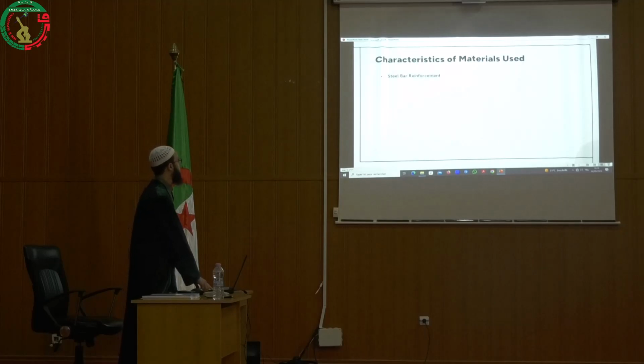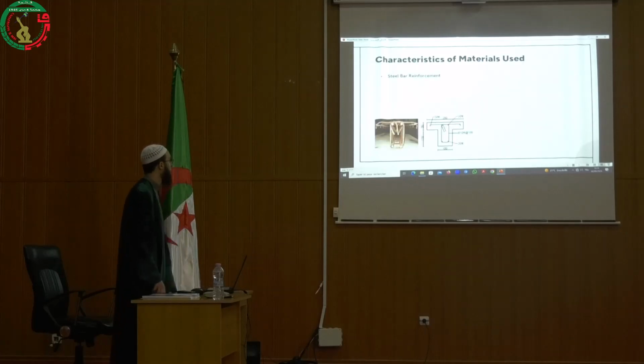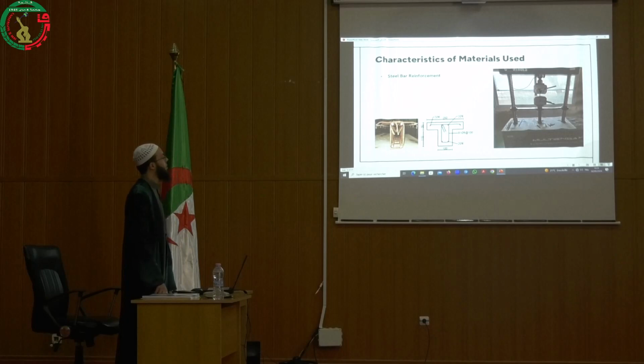Moving on to the steel bar reinforcements. We used identical 8 mm diameter bars for the tension zone, and 8 and 6 mm for the compression zone, with 11 vertical stirrups of 6 mm diameter and 100 mm spacing along the beam. These bars were carefully tested under tension to find out their mechanical properties, including yield strength, ultimate strength, Young's modulus, and the elongation, as illustrated in the following table.